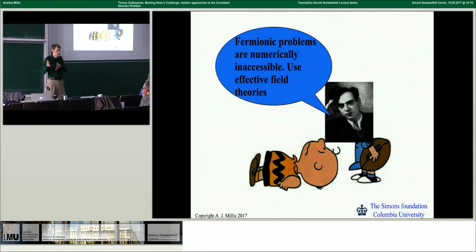To get entropies, you have to compute energies accurately enough that you can take a reasonable derivative. And this also relates to not having free energies: forces at higher temperatures are a bit awkward, because if you want to understand lattice deformations, you want forces, which means you want to take gradients of the free energy with respect to atomic positions, right? And we don't have the free energy, we have the energy, the internal energy. So that's a weakness.